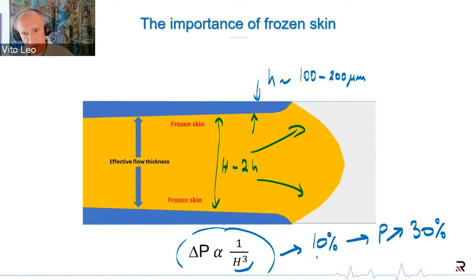But if you're struggling to make a critical, maybe medical part that has only 0.8 millimeter thickness, you are losing much more than 10%. So you will see an increase in pressure to fill that could be 50, 60, 70, 100% - a very strong increase in pressure. Of course, you could run your mold much hotter, but as you know, it doesn't make sense to run it really hot with a conventional flow process because the timing gets completely off and the economy collapses.